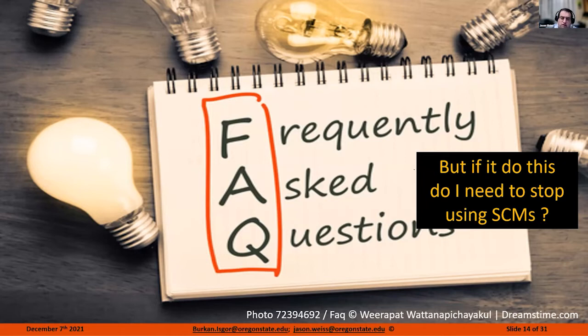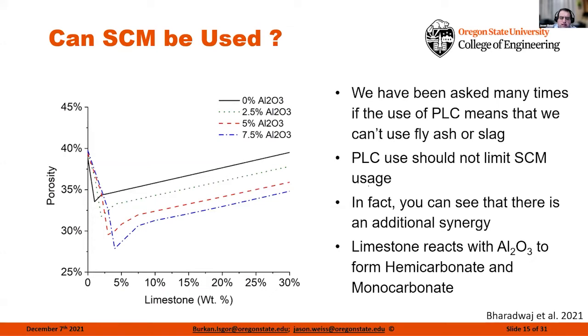Do not stop using your SCMs. Keep using your SCMs. And the reason for this is these SCMs can actually participate in these reactions. So if you have a siliceous SCM, silica fume, or a Type F fly ash, you see very similar porosity as you would have in the plain case. However, if you have reactive alumina in the system, what you'll notice is that in addition to seeing the benefit of reduced porosity, you'll see a further addition because you're stabilizing more of those phases. You see the porosity is further reduced. It's further reduced to a higher limestone content. And then what this carries over into is if we're looking to try to get equivalent performance, we could be going to higher and higher limestone contents if we do this. And this is really driving systems like the limestone calcined clay systems, like an LC3 system, that is really starting to say these are the directions we should be going, because we can get new reaction products that minimize porosity and give us good long-term strength based on some of these synergies.